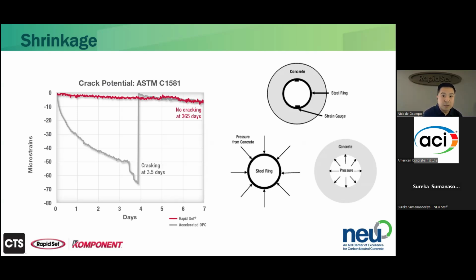So if we cast the concrete into the ring, it ends up looking like a big concrete donut, with the steel ring on the inside acting as a mold and a restraint, and there's a strain gauge attached to that internal ring. As the concrete shrinks, it presses on the steel ring, and that steel ring will contract with elastic contraction, measuring the microstrains, and eventually, as the pressure builds, the ring pushes back on the concrete.